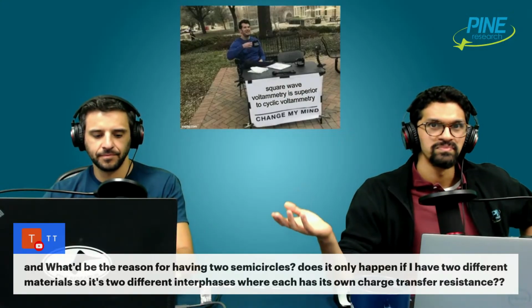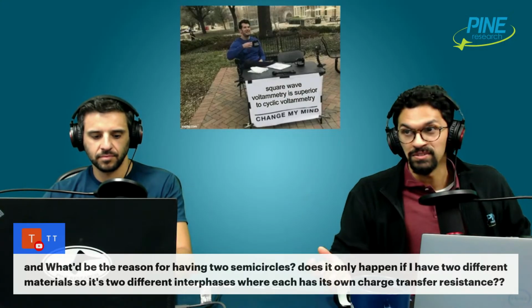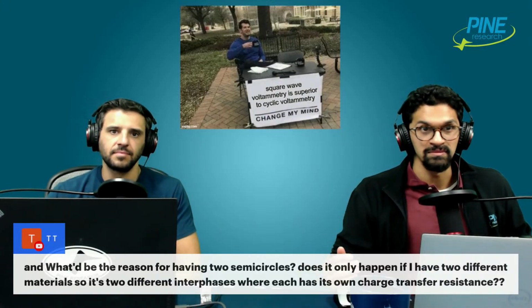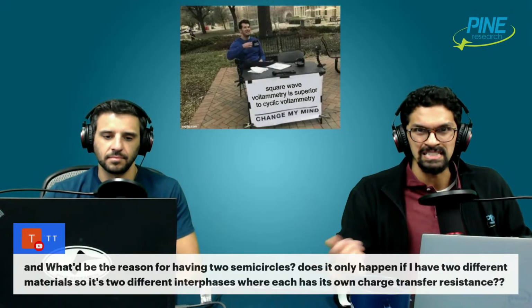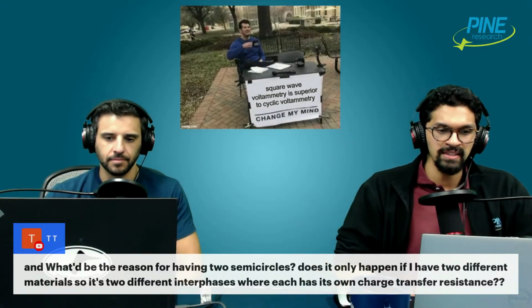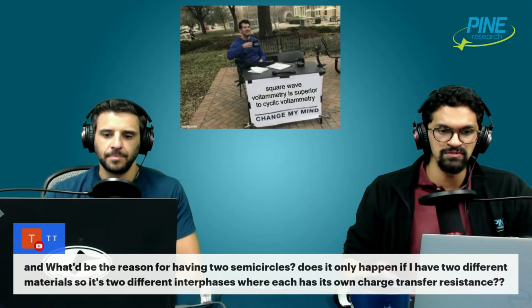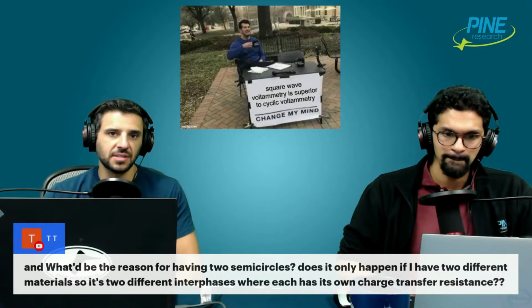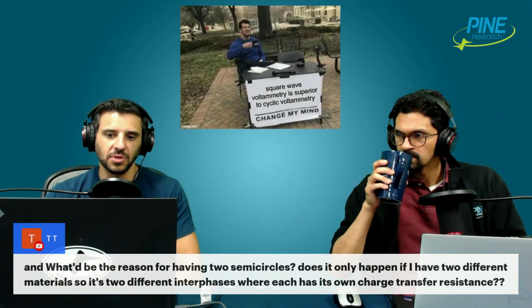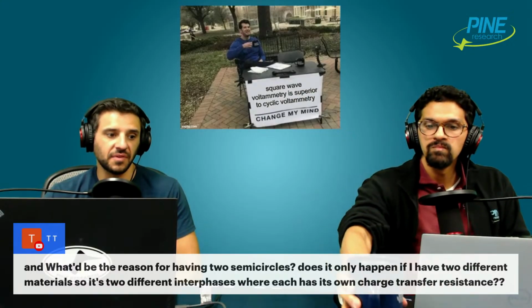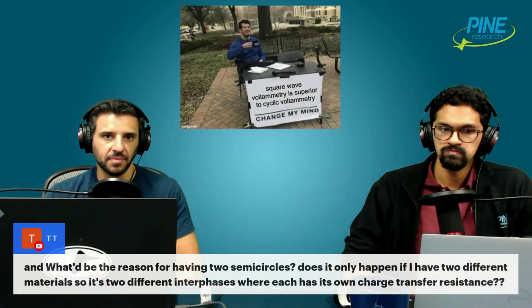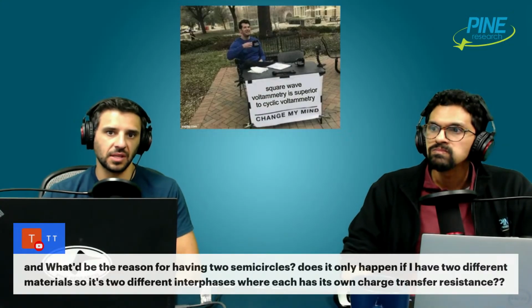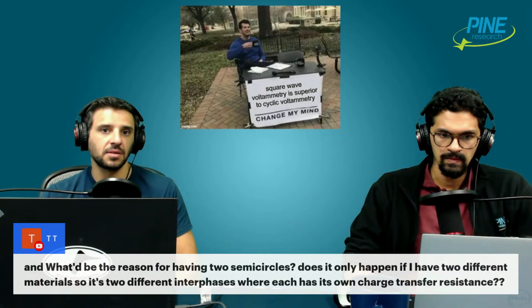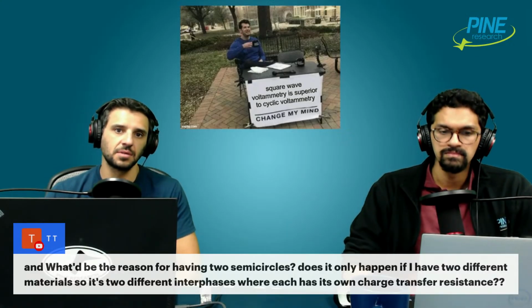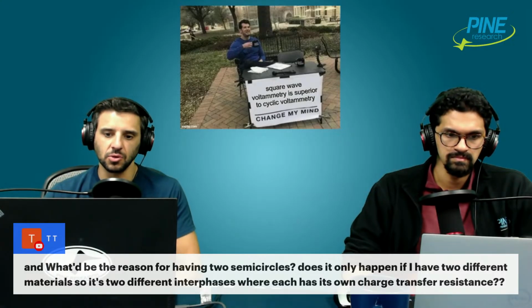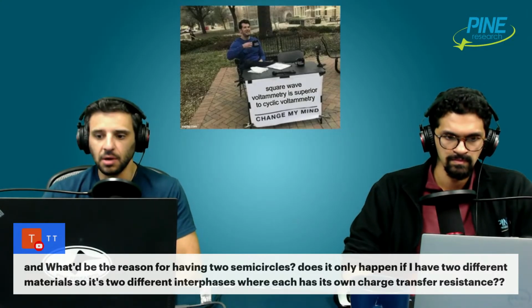Where they come from, could you have more things happening? Yeah, you can. If you have multiple processes, but some of them have the same time constants, you wouldn't be able to easily deconvolute them. But that is what it means fundamentally if you see 2 semicircles. And very often it's possible to come from what you've identified, which is to say you have 2 materials. You have like a substrate and a film. So you have an interface, some resistance and some capacitive effect between the substrate and the film. And then you have a second interface between the film and the electrolyte, for instance. So you have 2 interfaces, 2 time constants, 2 processes that can occur, right? So there you go. That could lead to 2 semicircles.